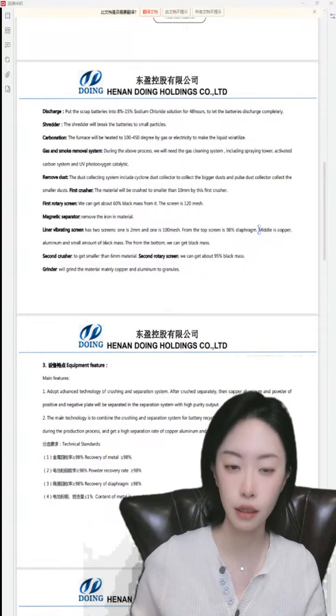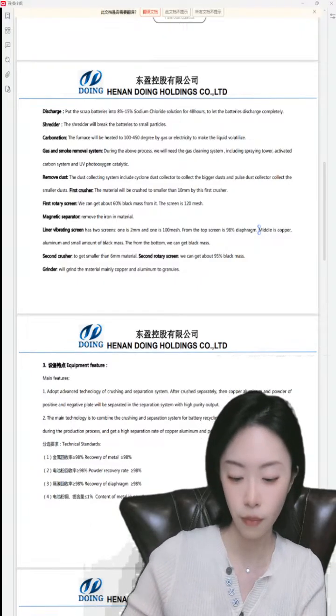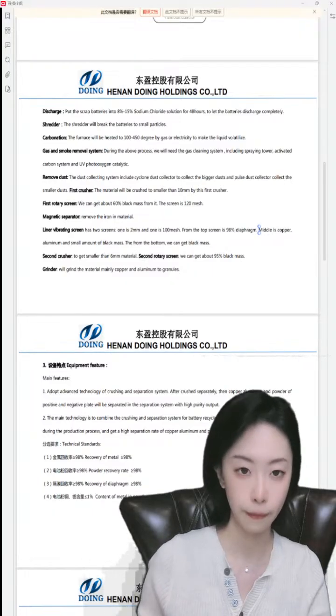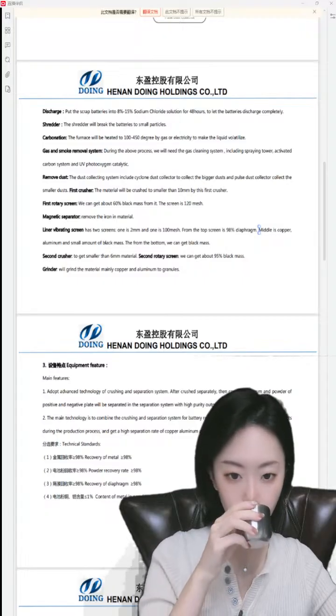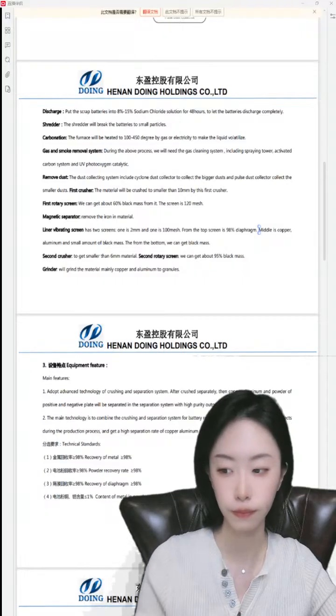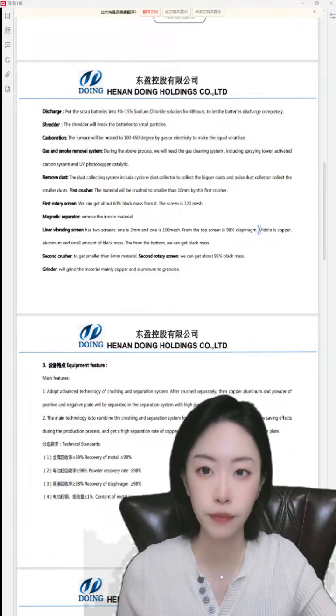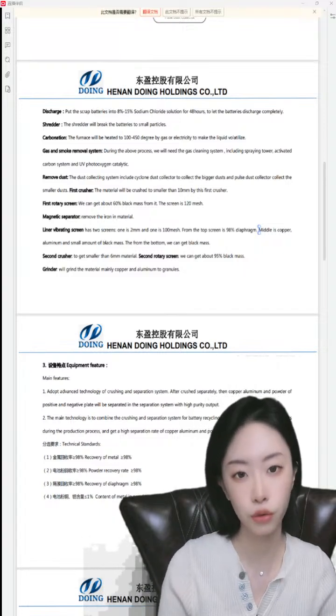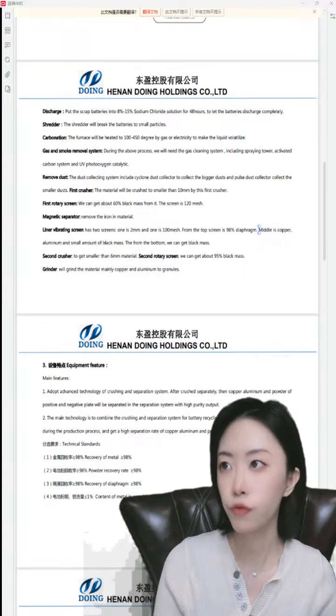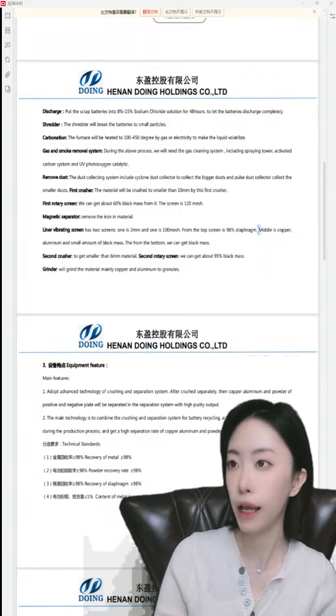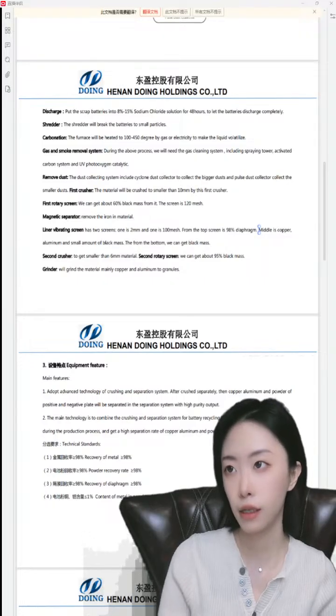And these are the several steps about the lithium battery. Like the first one is the discharging step, that will just put the scrap batteries into 8 to 15% sodium chloride solution for 48 hours, just nearly 2 days. Let the battery discharge completely.